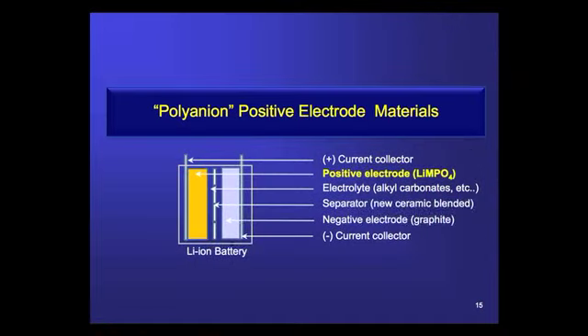So we always have to work within the thermodynamic range of the electrolyte, and that's what really limits the energy of the cell. So we have our gravimetric capacity that I just described, which is a combination of that at the positive and the negative electrode, and then the voltage of the cell gives us the total energy. So the capacity times the voltage is equivalent to the energy density. So the more we can separate these two, the higher the energy we can get, but we're ultimately limited by the electrolyte itself. So I'll be talking about positive electrode materials in today's lecture, exclusively, although there's certainly a lot of work to be done on the negative electrodes. And in this case, there is particularly a problem with, as I said, reactivity with the electrolyte with respect to oxidation. So surface coatings and other processes have to be implemented.